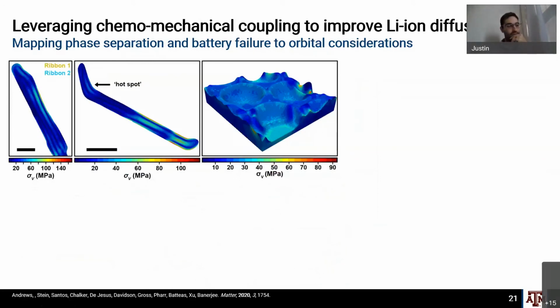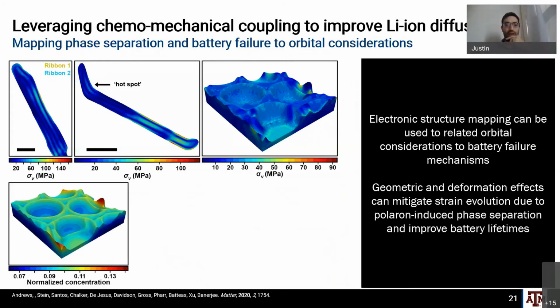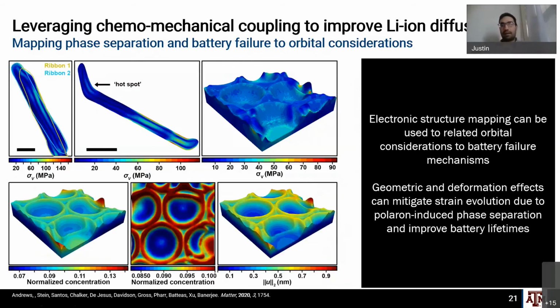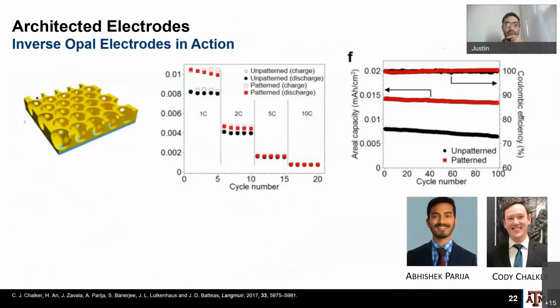And so in terms of what this looks like in terms of the strain, what we actually see is that not only does it react faster, but because of the decreased inhomogeneity, we also get decreased strain in the nanobowls. And so this is, admittedly, not just because of the decrease in the inhomogeneity, but also because the nanobowl or the inverse opal structure also has ample space to expand into the bowls and mitigate some of that strain that arises during cycling.